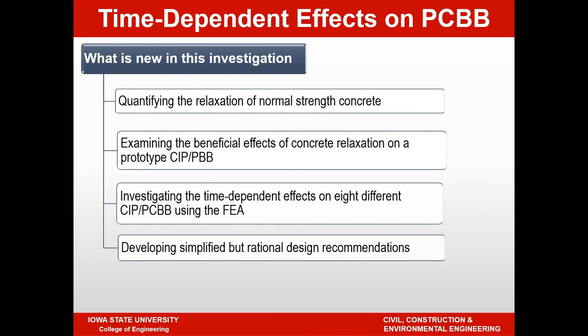So in our study, what we did was we wanted to capture the relaxation of concrete directly. The typical approach in the past has been you take a creep function and you reverse the creep function to establish a relaxation function. The creep and relaxation are treated as interchangeable, which is not a bad assumption. I think research in the past has shown they can be used interchangeably with appropriate reversal of the function. However, there has also been research published suggesting that